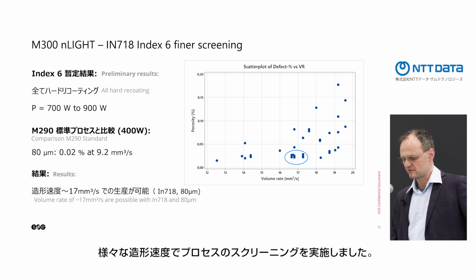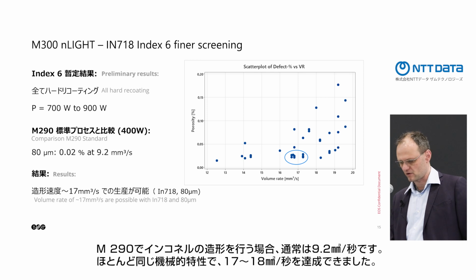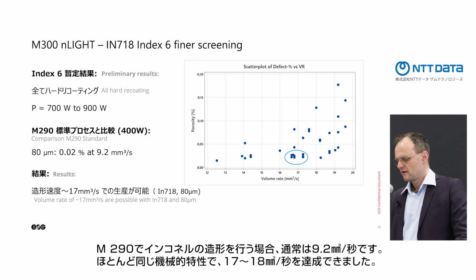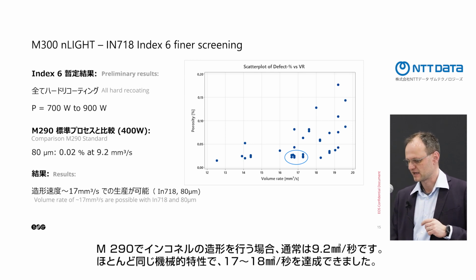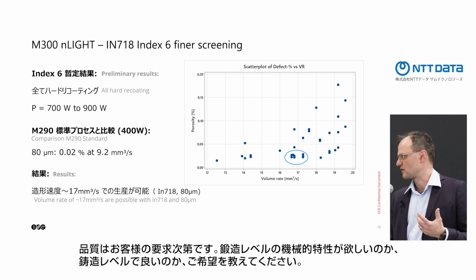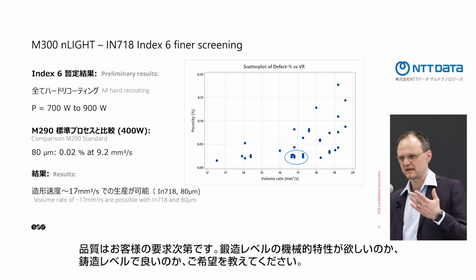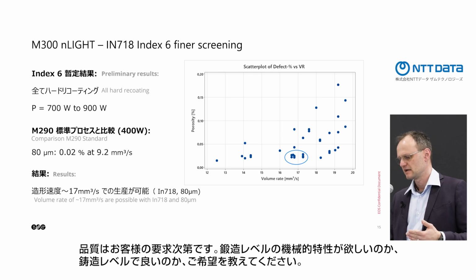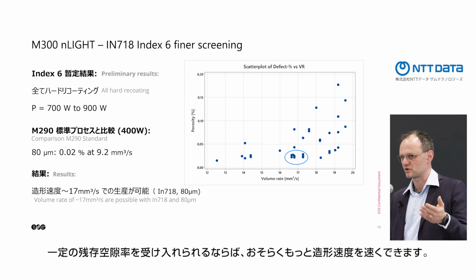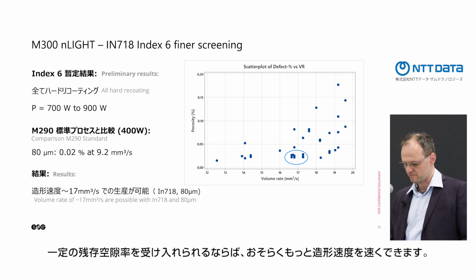Now, what we did is process screening with different volume rates. And you have to understand where we come from. On Inconel, on the M290, what we achieve is in the range of 9.2 cubic millimeters per second. With very similar mechanical properties, we are in the range of 17, maybe 18 cubic millimeters per second per laser that we can achieve. And the quality is always a function of the customer. So you tell us, do you want more forged mechanical properties or more cast grade? Maybe if you can accept a certain remaining porosity, the performance can get even higher.